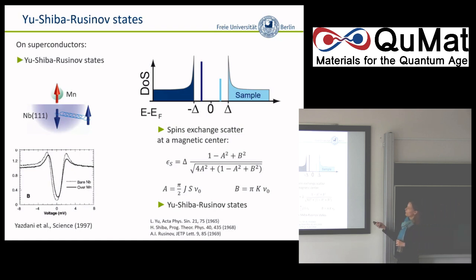But you also see that, well, I sketched them here so that they don't have to be completely symmetric in intensity anymore. The reason is that there's a second term that you could also have, and this is potential scattering. This potential scattering I call here K. And essentially, in a simple picture, like in Coulomb scattering also, it's maybe easier to put an electron than to put a hole. And therefore, the wave functions associated with this state have different weight at the positive and the negative part.